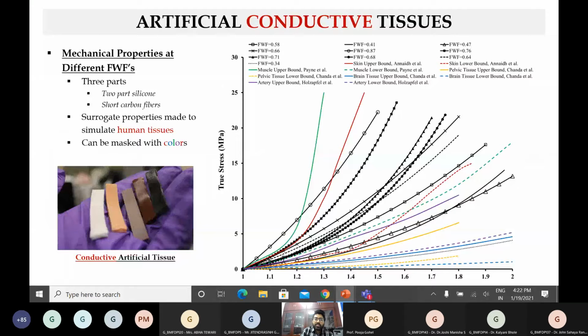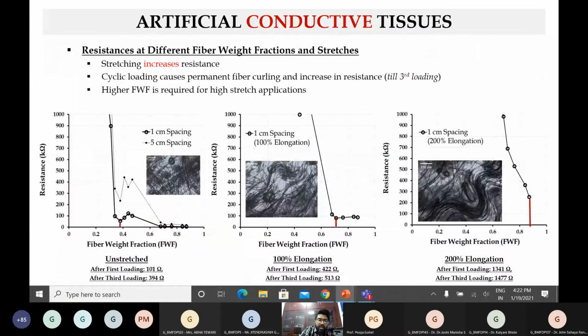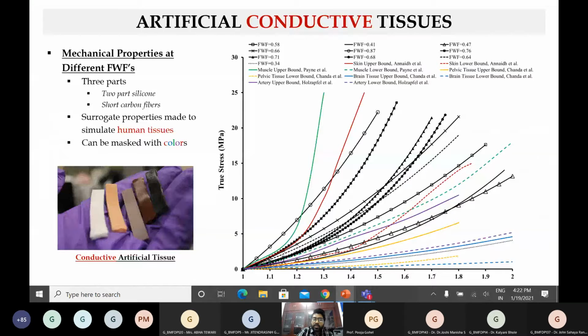The second part is now, that is all great. We have achieved electrical conductivity. We have found fiber weight fractions which are optimized. Now, the second task was we wanted to do all these tests with this fiber weight fraction. If we remember, the fiber weight fraction has to be at least 0.4. Anything above that is good. So we started with, let's say, 0.4, and we looked at all the fiber weight fractions above that and started comparing them.